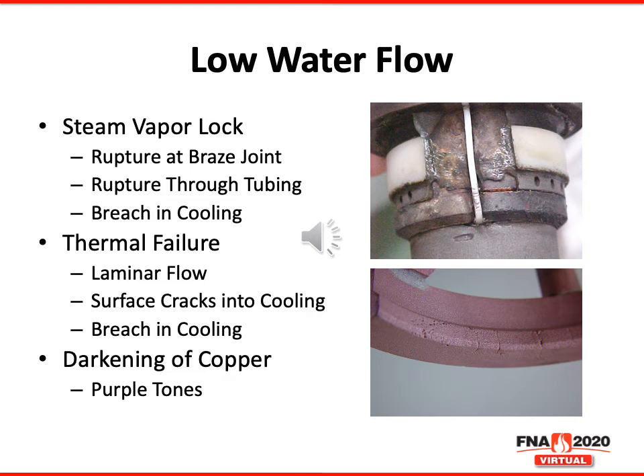Problems with a cooling system can be detrimental to the performance and longevity of induction tooling components. Contamination in the cooling system can lead to low water flow. Problems with the water pump can also cause a low water flow condition. Low water flow can cause a steam vapor lock in the inductor coil, leading to a rupture at a braze joint, a rupture through the tubing in a fabricated inductor coil, or a breach in the copper exposing the cooling chamber. Low water flow can also cause laminar flow internally, which leads to thermal failure resulting in exposed surface cracks through to the cooling chamber.